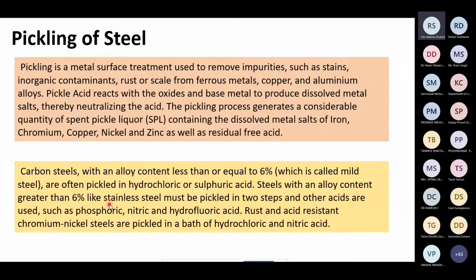Then another is the pickling of the steel. Pickling means the steel is kept inside an acidic environment for a certain time. Why? Because the final finish of the steel requires different types of treatment. If you require steel with a glossy surface or matte surface, you need to treat it with different acids. The steel is kept inside a bath of nitric acid, sulfuric acid or hydrochloric acid for a certain time duration, in sequence or maybe in parallel. Then you have the metal surface treated. Now this treated metal surface is a finished product.